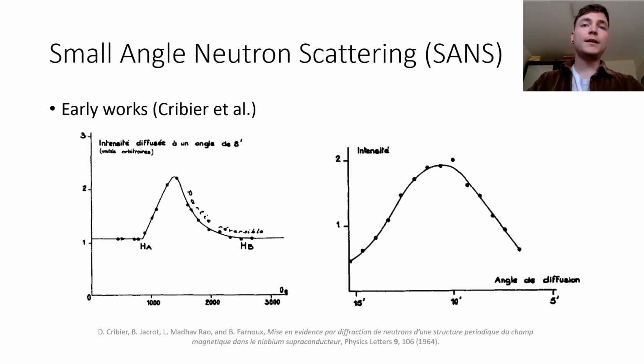Right, so the Abrikosov theory predicted a two-dimensional grid of penetrating external field flux tubes, through each of which one field quantum passes. And de Gennes proposed in 1964 to use neutron diffraction methods to try and measure this periodicity. And neutron scattering should resonate in your ears, because that's already a presentation that we heard from Uchin. And this was then put into practice by Cribier using a technique on a pure niobium superconductor.